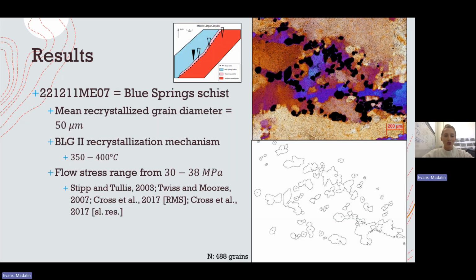So transitioning more so into the microstructural analysis as well as the paleopiezometry, the samples that were selected for piezometry are seen up here. And as you can see, we have gotten a sample for each lithology. So the first sample here, the 07 sample, is located in the Blue Spring schist, and it had a mean recrystallized grain diameter of 50 microns.